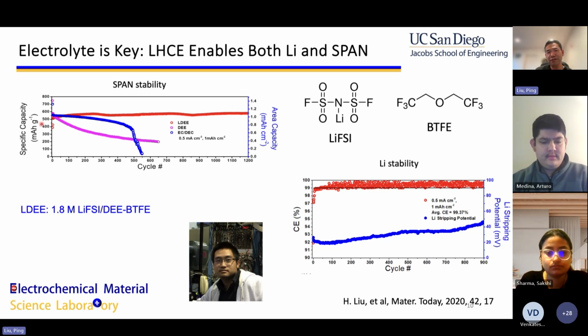I can tell you that if you find the right electrolyte, and the electrolyte we work on is what we call a localized high concentration electrolyte, it's lithium FSI dissolved in diethyl ether mixed with BTFE, which is a non-solvent. This type of electrolyte innovation has been the essence of the work we do, not necessarily on the SPAN material itself, but to allow the SPAN material to work as intended. You will see that this SPAN material cycles for 1,200 cycles in this electrolyte without any decay.